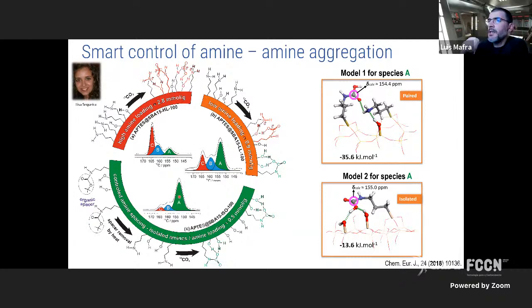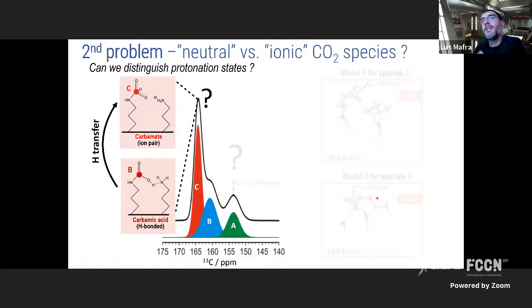So this leads us to think that A must be an isolated amine, because you are favoring isolated amines when you do this transformation of your surface. Okay, so based on these experiments, we can discard this model here, and we are pretty much sure that we have an isolated amine that is hydrogen bonded to the walls of the material. Another problem is to really prove if this intense peak C is a neutral hydrogen bonded carbamic acid, or just an ion pair where the proton has been transferred to the negative amine, or maybe could also be a zwitterionic entity. This is tough to prove.